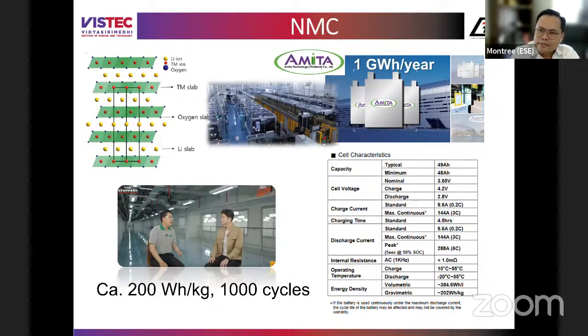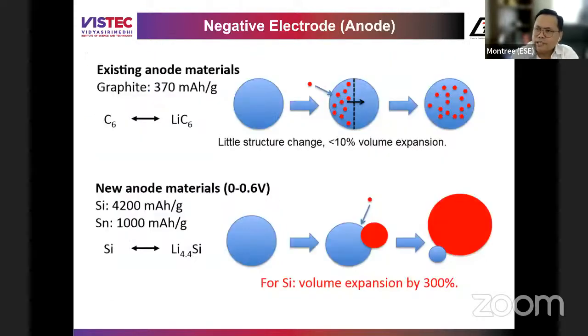So economy of scale and so on become really big issues. If you go to the graphite, for example, at the anode, by its idea, when we put lithium inside the graphite, the volume expansion is less than 10%. So the volume of the battery is not really expanded, right? Inside the volume of the anode side, not expanded.